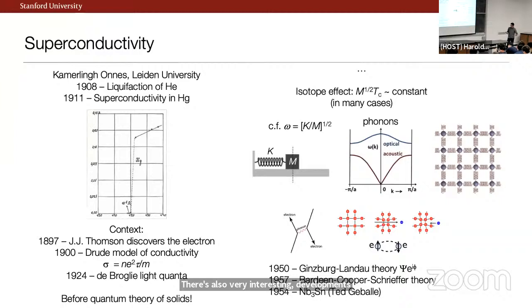And so while there are lots of experiments I could tell you about, one of the key ones in the development of these ideas was a so-called isotope effect. People found that in many, but not all superconductors, if you could change the isotope, the square root of that mass times Tc is roughly constant, okay? And so that led a lot of people to zoom in on saying that electron-phonon coupling, coupling to lattice vibrations must be important.